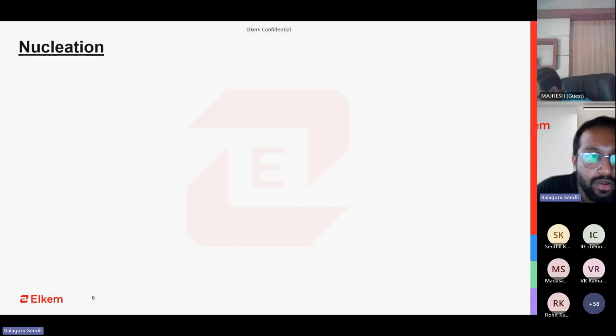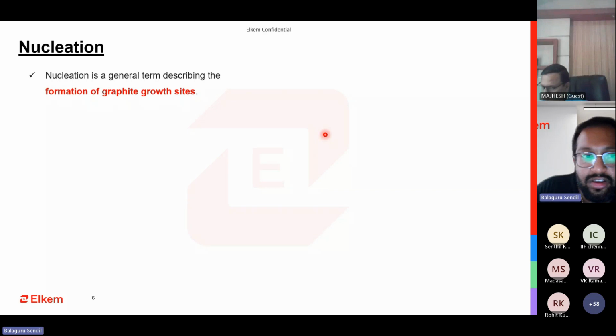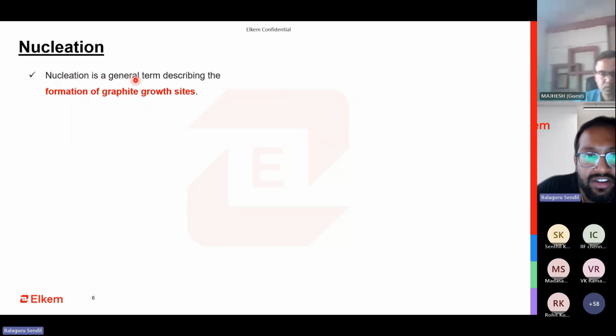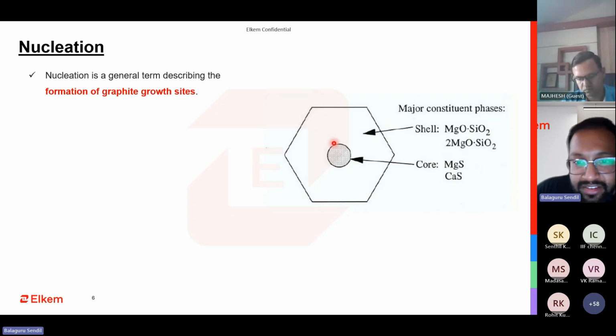So again, what is nucleation? Nucleation, as we discussed earlier, is the general term describing the formation of graphite growing sites. Basically, this is a site on which the graphite starts to grow. So it is the formation or creation of sites on which the carbon which is coming out wants to settle somewhere and be stable. If you have these nucleating sites, the carbon will voluntarily come and settle there and come out as graphite. Unfortunately, if you don't have enough of these sites, then the carbon can come out as carbides because not enough graphite growth sites are formed.